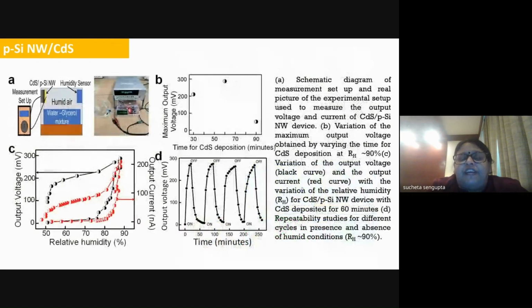Now, cadmium sulfide is itself known to be a very hygroscopic material, so it is very popularly used as humidity sensors. So what we did is we tried to extend it more. We put the device of this cadmium sulfide and silicon nanowire heterostructure inside a humidity chamber. We tried to vary the water humidity inside this vessel by controlling the water glycerol mixture, and we tried to measure the voltage which is generated.